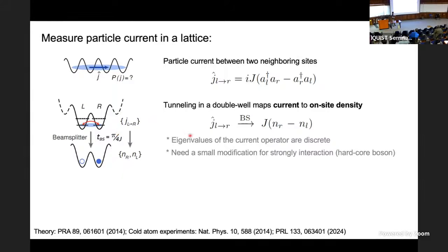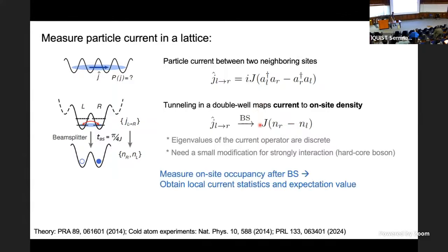One is that we have a strongly interacting system, so there need to be some small modifications in the scheme. And the other thing I want to point out is this mapping from here. You can see that the current actually also should have discrete eigenvalues, right? Which are integer multiples because of this n difference times J. But the upshot here is we have a way, by measuring on-site population in the lattice after this beam splitter operation, after this tunneling, which allows us to directly extract the in-situ current, not only the expectation value of the current, but also quantum fluctuations in the current. Okay. In the interest of time, I'm just going to stop there.